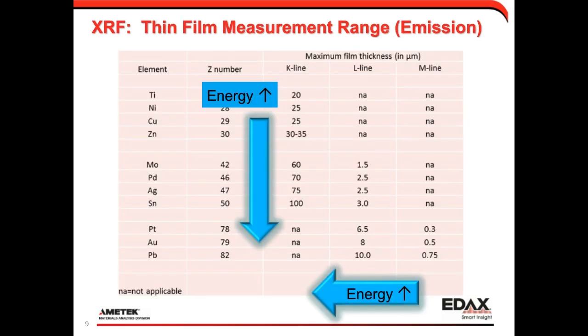Okay, so this table here is going to give us an idea of the range of coating thickness that we can measure for different elements and different kinds of X-ray lines. If you look over on the left, we're running from titanium at the top down to heavier and heavier elements. And in general, as we go from the top to the bottom, we're looking at X-rays that are more energetic. On the right, you have columns for the K-line X-rays, the L-line X-rays, the M-line X-rays.